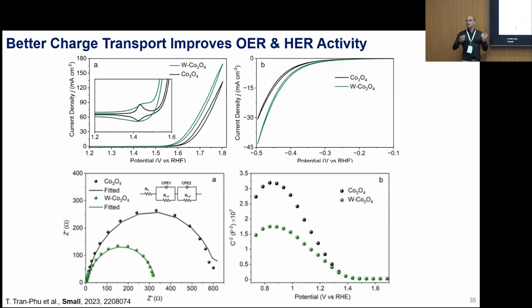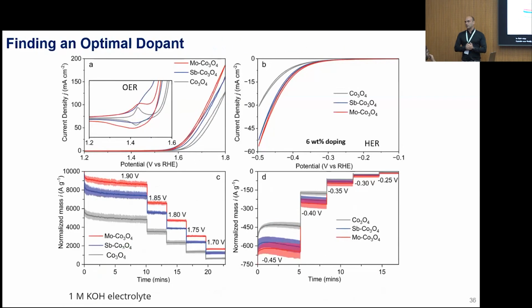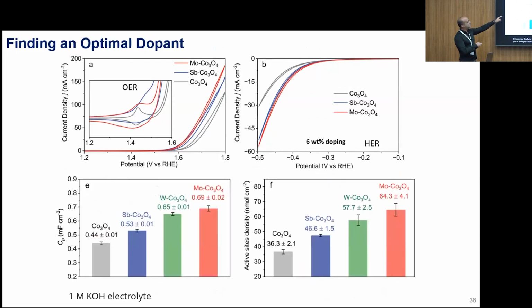Now, finally, is tungsten the best? So we started exploring a lot of dopants. Here is just an example, antimony and molybdenum. And as you can see, it gets better and better, and actually molybdenum is working quite well. So now we have an alkaline electrocatalyst, which works well for OER and HER reaction and is quite cheap.